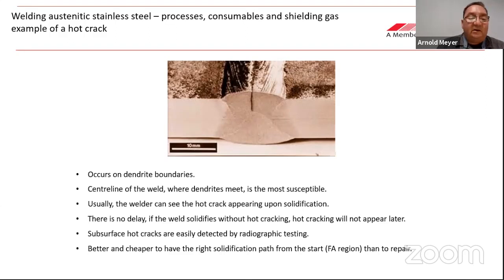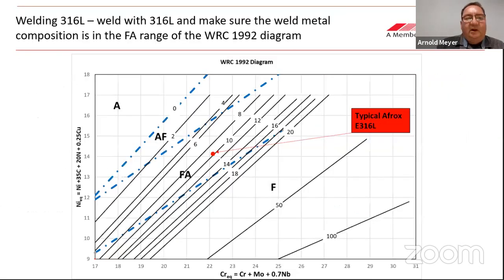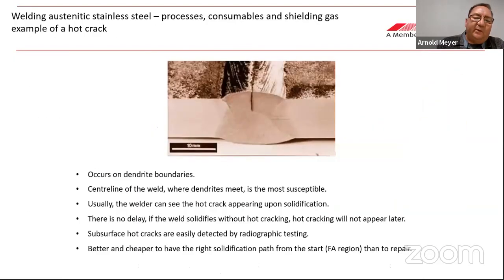Usually the welder can see it appear. There's no delay. It appears on solidification. Once it's solidified, there's no hot crack. A hot crack will not appear after solidification. Sometimes you can't see them on the surface. Then you need to do radiographic testing. Most of the time they're open to the surface though. It's better and cheaper to have the right solidification path, in other words, make sure that your consumable is in the FA region of the 1992 diagram, than to repair afterwards. Welding repairs are very expensive.